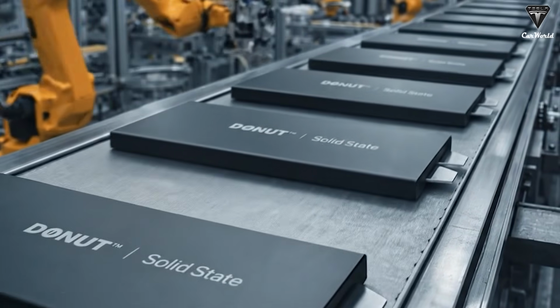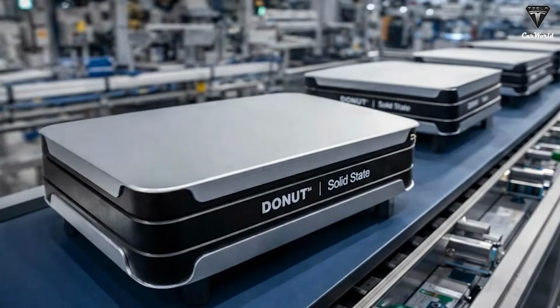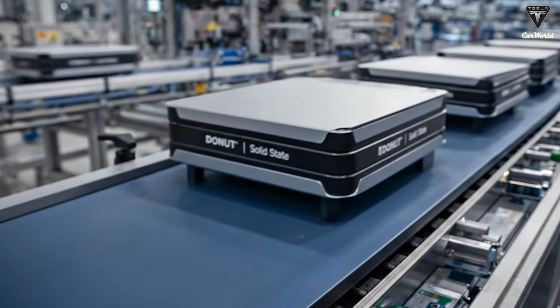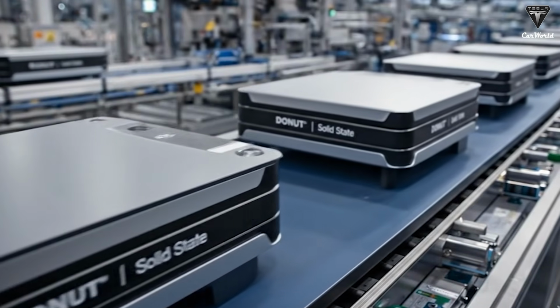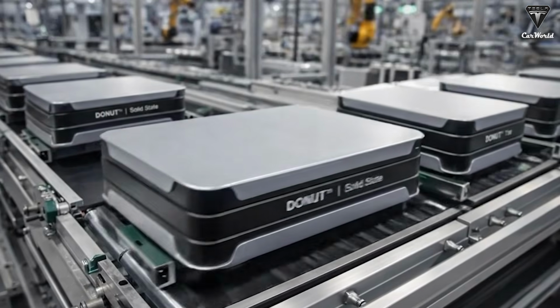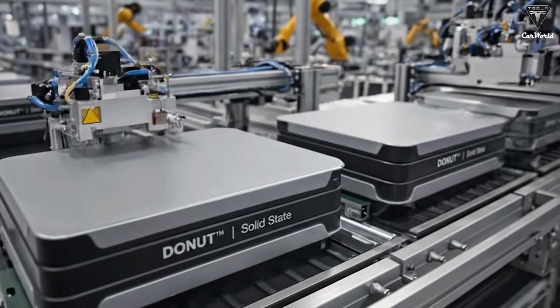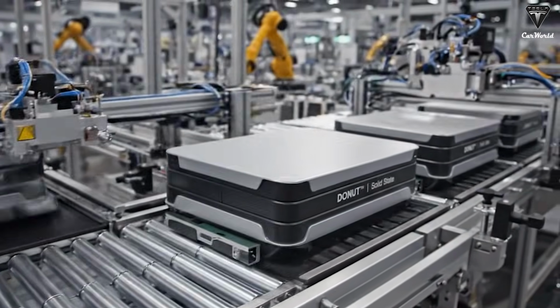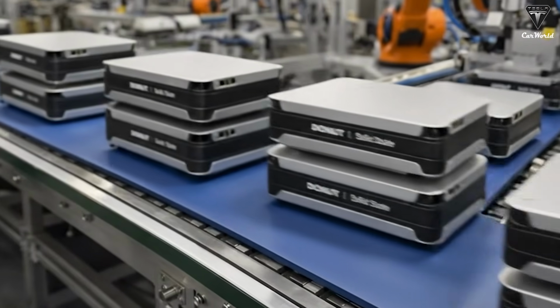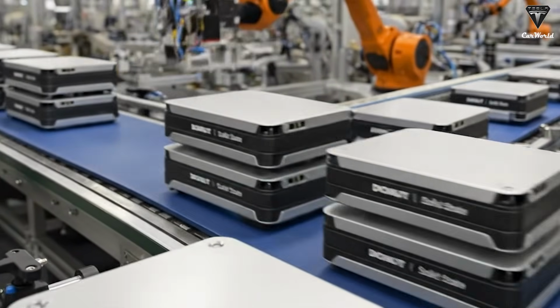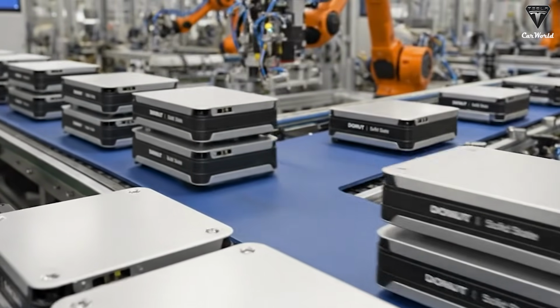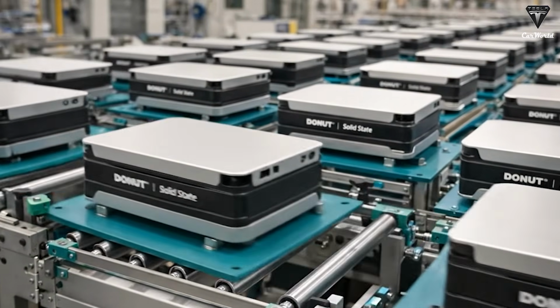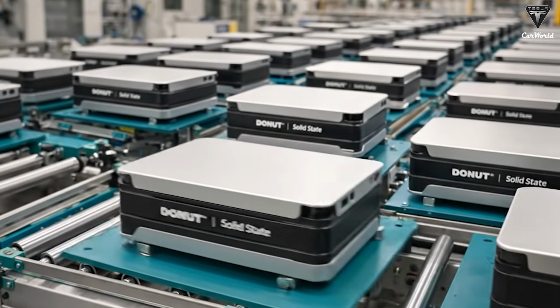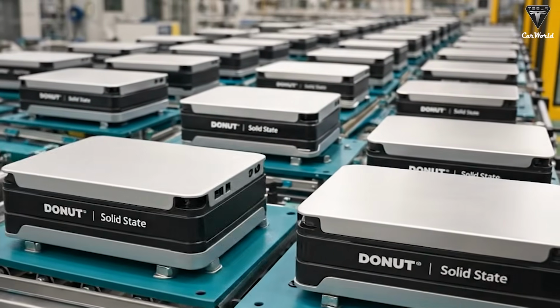But in reality, while capacitors do charge quickly and boast long lifespans, they fail catastrophically in one critical area: energy density. Even the most advanced supercapacitors rarely exceed 10 to 20 watt-hour per kilogram. Donut Lab, by contrast, claims an energy density of 400 watt-hour per kilogram, nearly twice that of Tesla's best cylindrical cells and far beyond what LFP or sodium-ion technologies can currently achieve. If Donut Lab's battery truly employs an amorphous ceramic structure, such as amorphous titanium dioxide, then the usual trade-offs may no longer apply in the same way. That alone could explain the extremely high cycle life without resorting to speculative or science fiction physics.